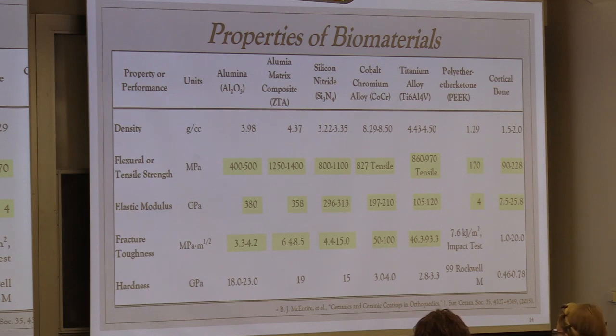And then on the far right over there is the properties for cortical bone, because all of these materials in some way or another have to interface with bone structure itself. So the most apparent thing that you can see if you contrast and look at all of these things is that the ceramic materials actually have the overall lowest fracture toughness, particularly when you compare it to the metals. So they're brittle materials, and they fail that way. They fail brittly, they fail by crack propagation.